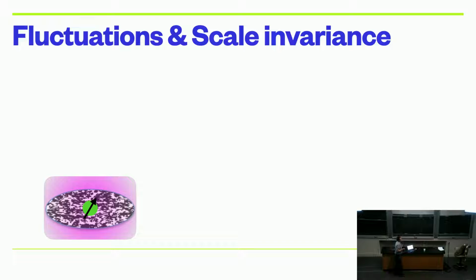Well, something very interesting happens as you approach a phase transition, and that's what's known as fluctuations. Basically, it's where those spins start to see each other in a local environment, and they start to move in harmony. But they haven't fully formed a ferromagnet in this case. And some of them will be down. So what I'm plotting here in the mean field is what these fluctuations between spin up in black and, let's say, spin down in white will look like as you approach this phase transition.